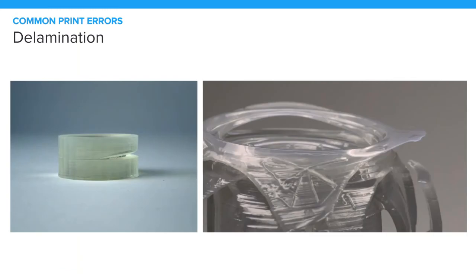Delamination is our next one. It's characterized by one or more layers peeling away from the others. It's relatively rare, but it can happen when a tank or optical surface is dirty or damaged, or your build platform is actually loose. An improperly supported or oriented part could actually also play into seeing delamination in your prints. But the most common reason for this is when a print is stopped or paused for several hours. So in a Form 1, if you have a resin fill-up pause that lasts too long, or if you have a Form 2 and you pause it and you just walk away from the machine, that can cause that.